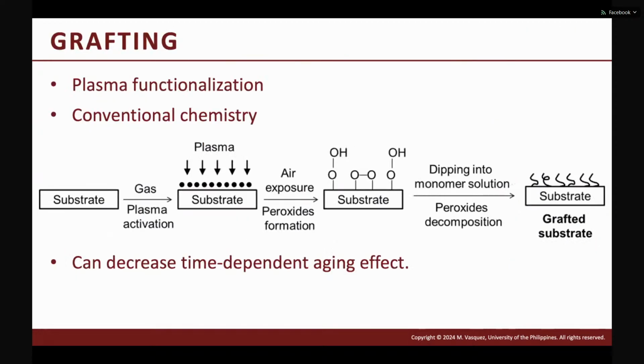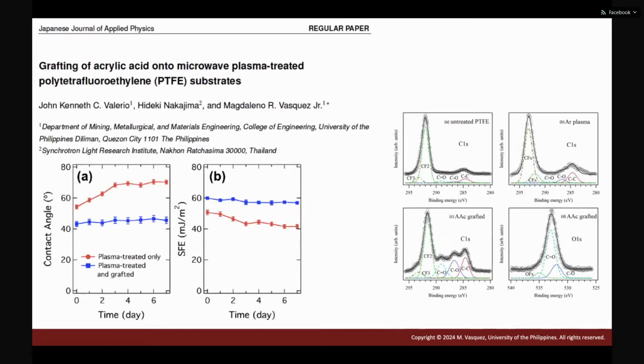Another important application of surface modification is grafting. It's a two-step process. First, you functionalize the surface, and then you rely on conventional chemistry to improve the addition or attachment of a functional group. With grafting, you remove the dependence, or decrease the time-dependent aging effect on polymeric materials. So that means for grafting, the effect is more long-term.